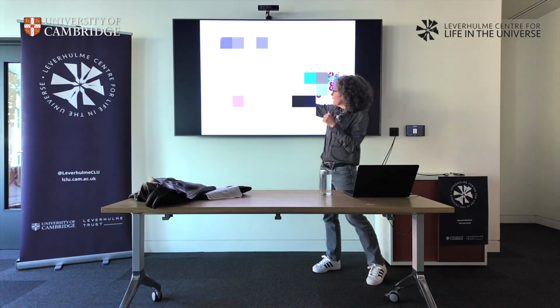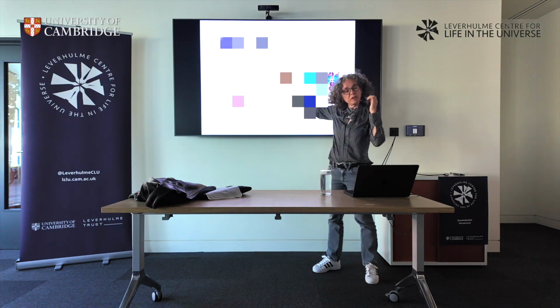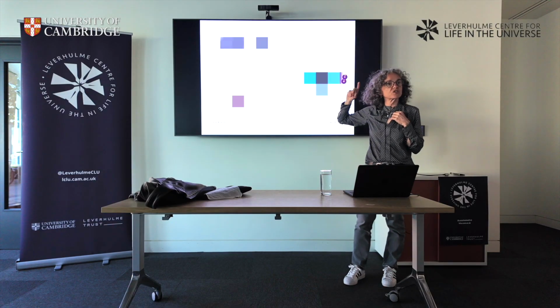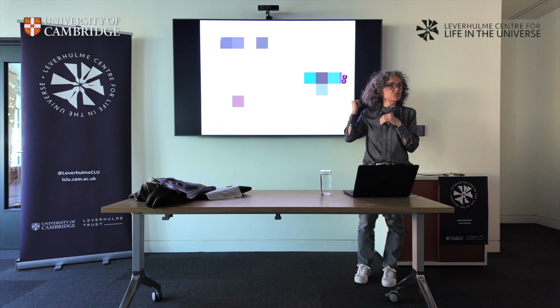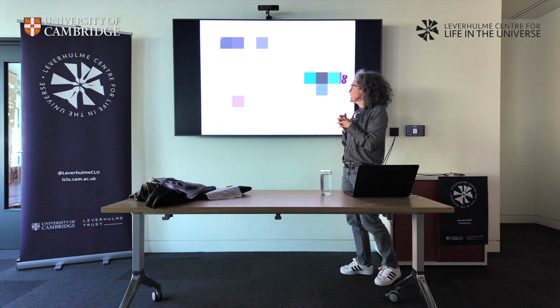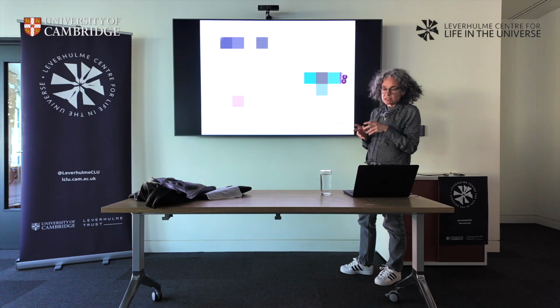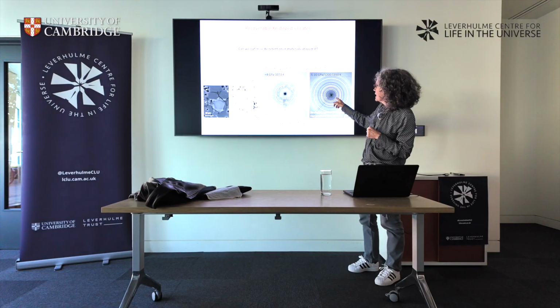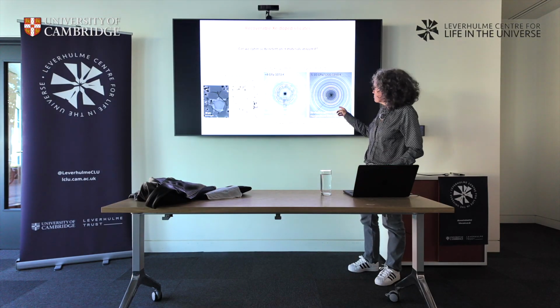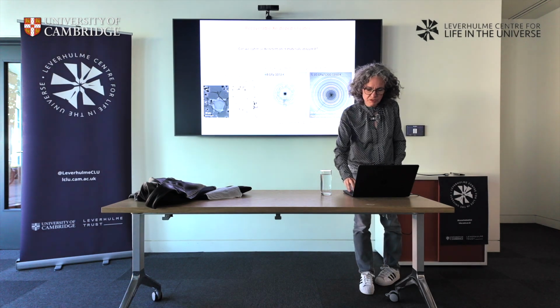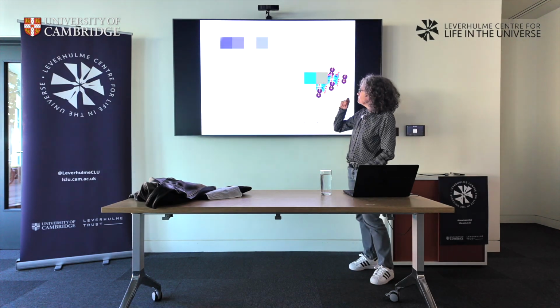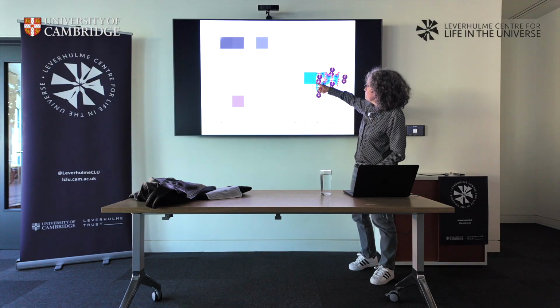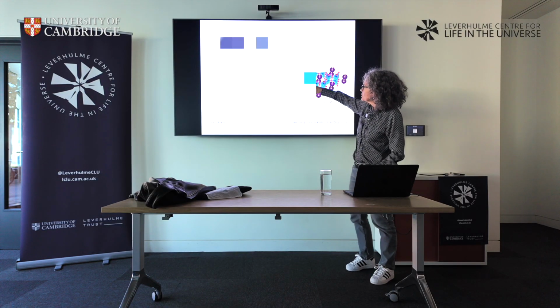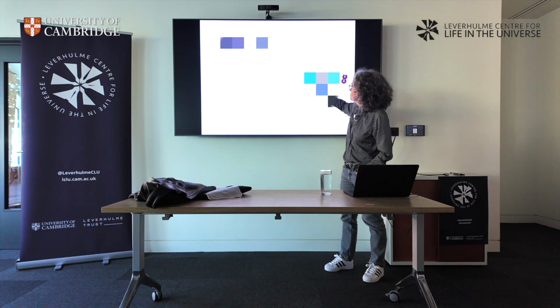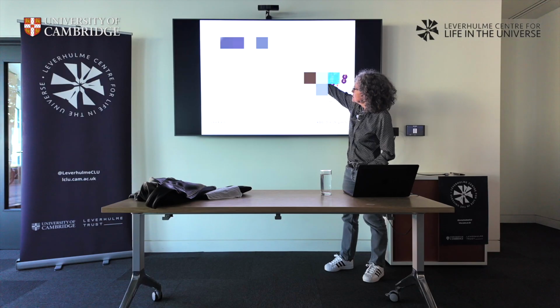Okay, so we have this distance, 3.2 angstrom, which is much larger than what I showed you before in quartz and olivine, where it was 2 angstrom. That's much larger, so it's certainly a weaker interaction. It's there, but it's weaker. I'm not going to show it, but we also processed nice powder quality X-ray diffraction data, and basically the only possibility is that xenon goes into the potassium site, and this gives you this distance between potassium and oxygen of 3.2 angstrom.